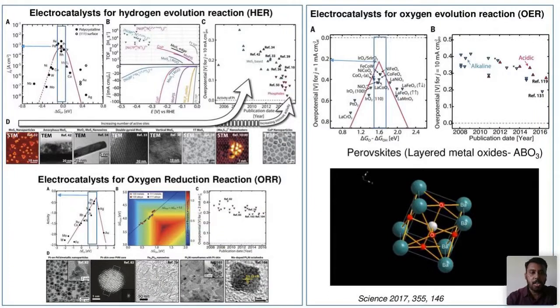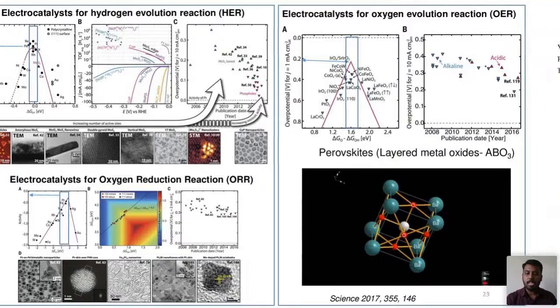What are the best electrocatalysts for hydrogen evolution? What are the best materials for oxygen evolution and oxygen reduction reaction? The best benchmark for ORR and OER is platinum and palladium. Also for hydrogen evolution, the best material is platinum, and molybdenum sulfide is the inexpensive material. People try to develop carbon-based composites, alloyed with other metals, and different metals can be used, and based on the structure also you can tune the activity. For oxygen evolution, oxides and hydroxides are very good materials, and perovskites are very good materials for oxygen evolution.